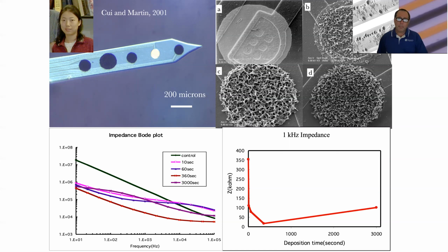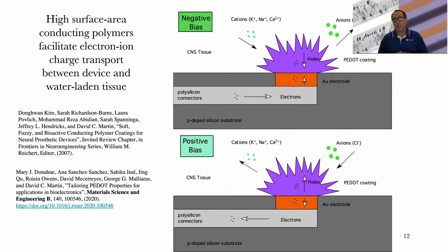And so if you look at the impedance at 1,000 hertz as a function of time, you see that it drops dramatically, sometimes 2 orders of magnitude, sometimes 3, depending upon the precise conditions. And the reason for this, you can appreciate just from looking at the SEM images in the upper right. So the conjugated polymer is not a better conductor than the underlying metal, but it has a whole lot of surface area. And so we're creating a thin film that's essentially acting, as my colleague George Malliaras likes to call it, as a volumetric capacitor.